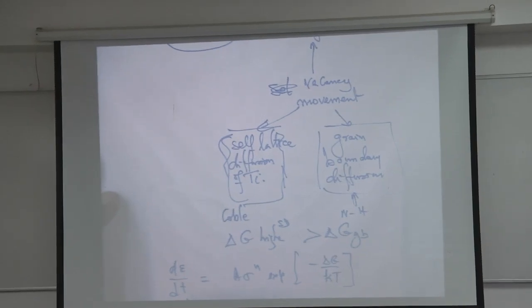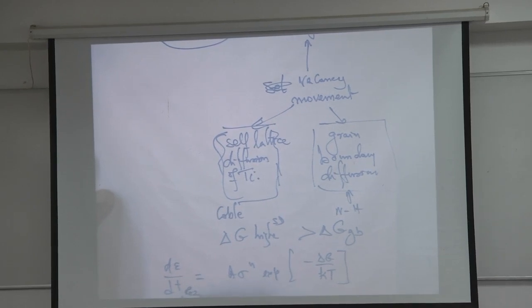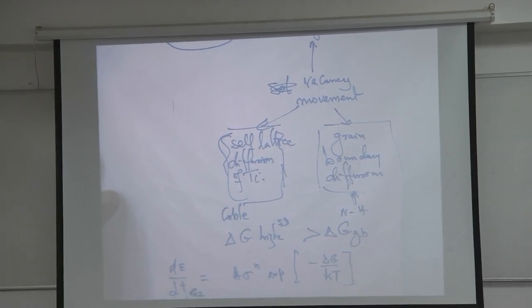I'm going to make something up. Somebody, you're asking questions, I'm going to make up an answer for you. I'm going to write this equation as d epsilon dt is equal to A sigma raised to n exponential minus delta G over kT, right? So my d epsilon, from epsilon 1 to epsilon 2, that is my increment in the creep deformation, is a function of, I have a constant stress. This whole thing is constant. Constant temperature test, constant stress test. My process is the same. Everything is a constant. I want to put here constant dt. So A prime t is equal to epsilon.